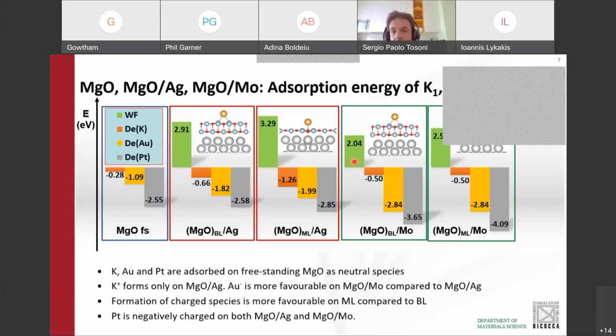And here on molybdenum, the work function is much smaller compared to silver-supported MgO, and as a result, we do not have a full ionization of potassium, and the binding energy is only slightly larger compared to the freestanding case. Gold displays in a way the opposite behavior, and the adsorption energy is larger on substrate with small work function.